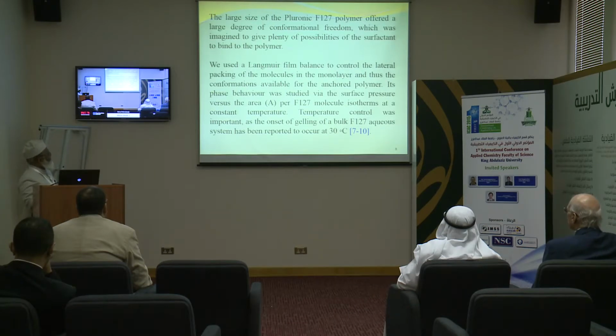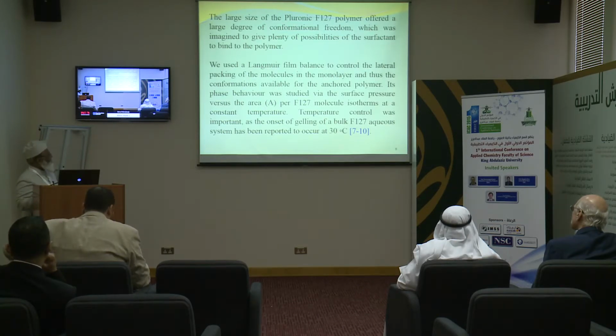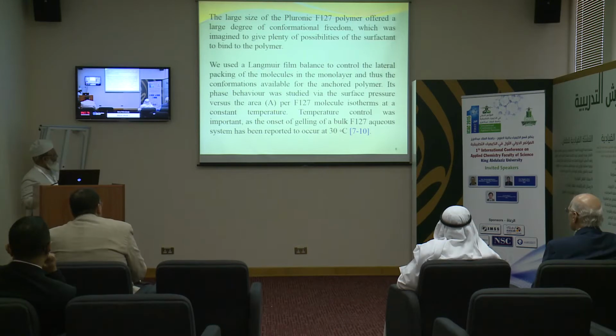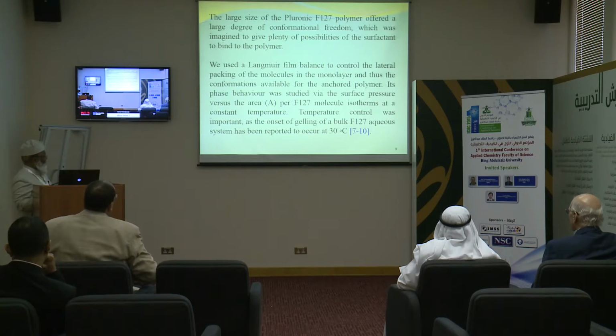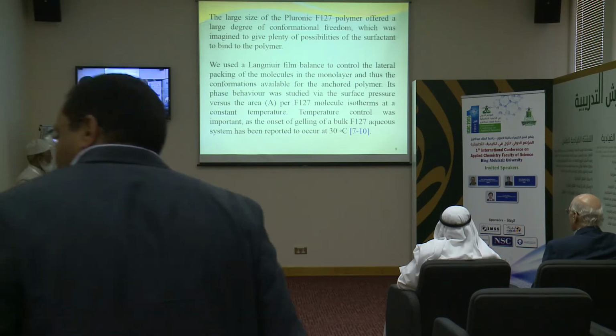The large size of the Pluronic molecule offered a large degree of conformational freedom, which was imagined to give plenty of possibilities of surfactant binding to the polymer. We used a Langmuir film balance to control the lateral packing of the molecules in the monolayer, and thus the conformations available for the anchored polymer. Its phase behavior was studied via the surface pressure versus the area per molecule isotherm at a constant temperature.